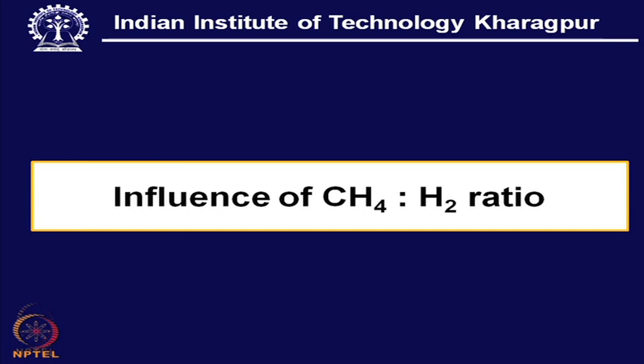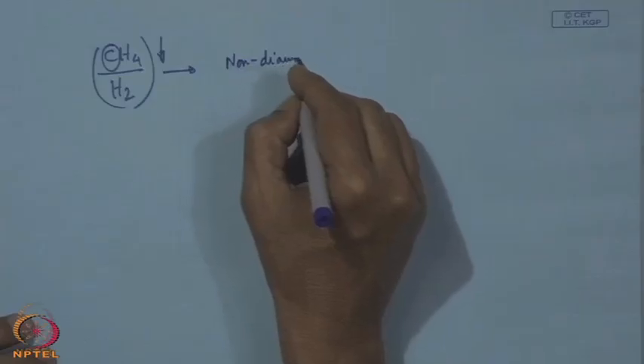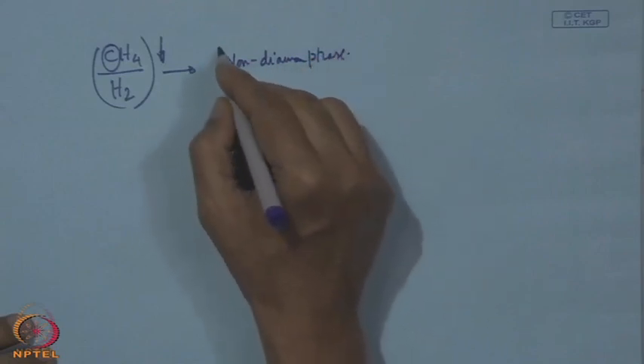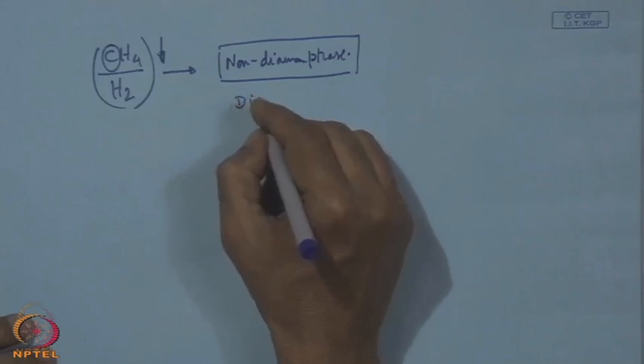Influence of CH4 to H2. This is a very important consideration. CH4 to H2. Now, higher CH4 concentration means a higher percentage of carbon, so we have more carbon available for the growth of the coating. However, it is found that if we have too much methane in proportion to hydrogen, we may end up with a non-diamond phase. But what do we want? We want the diamond phase.